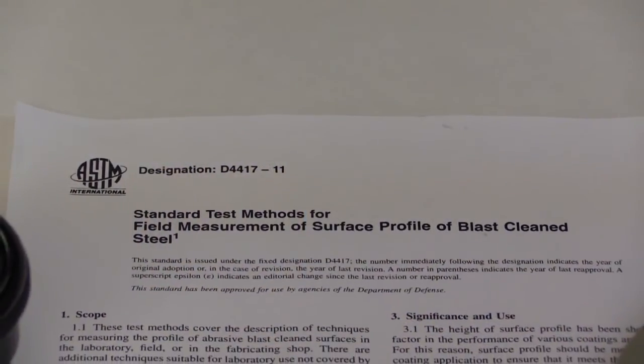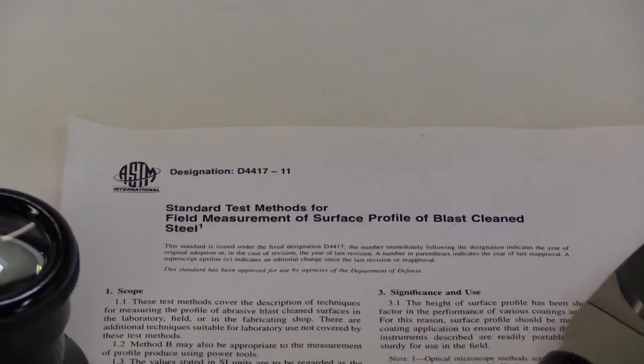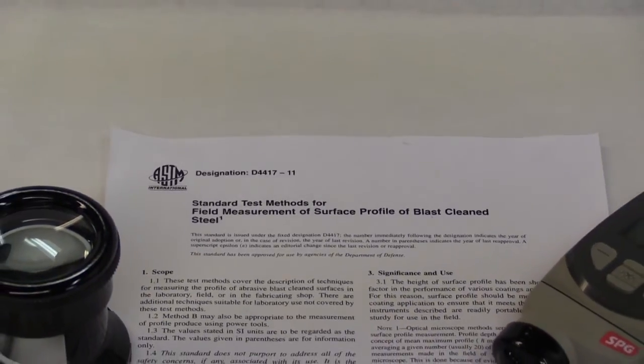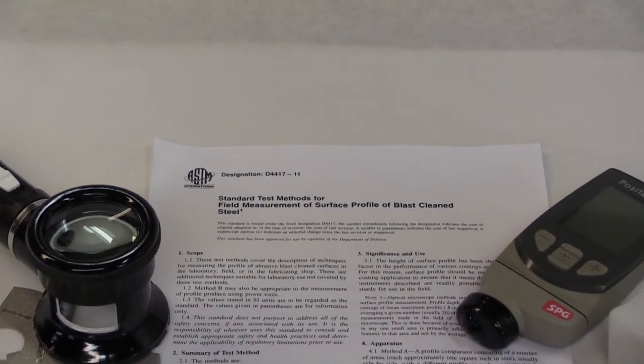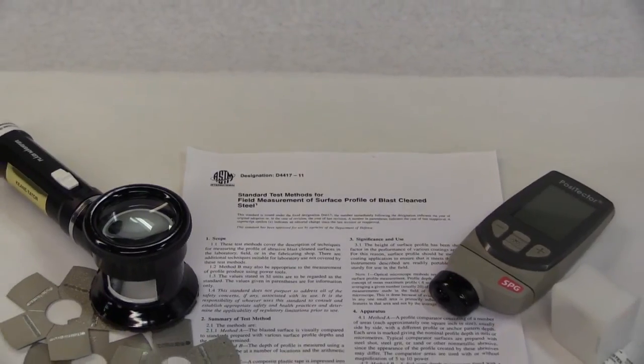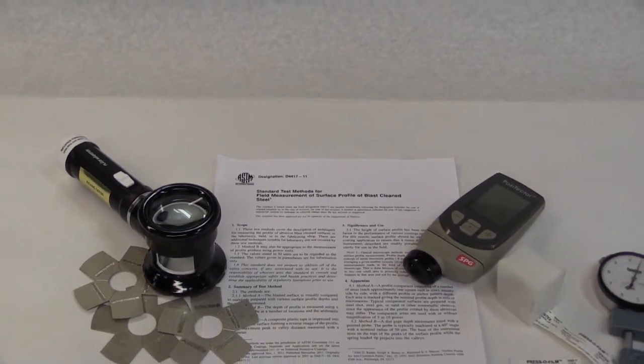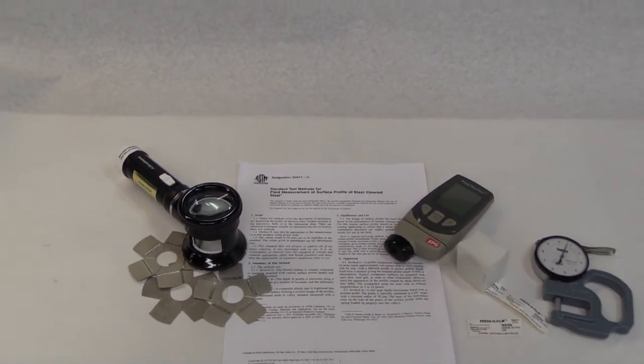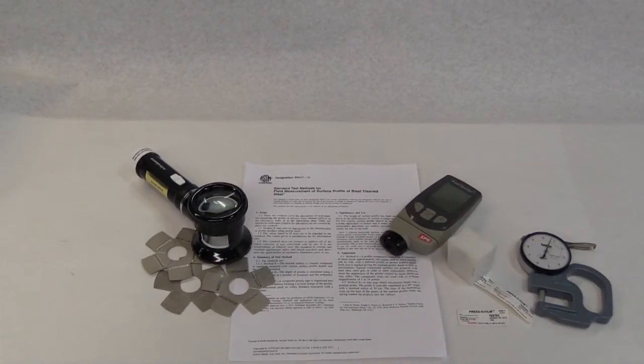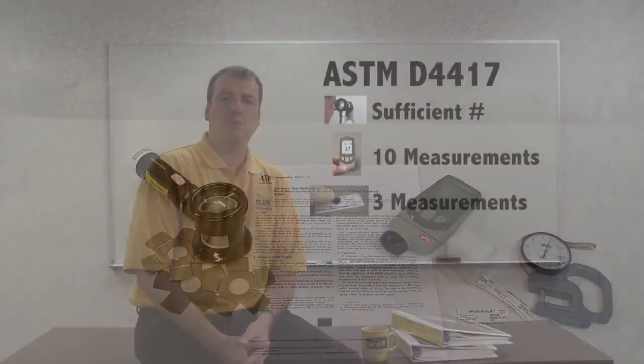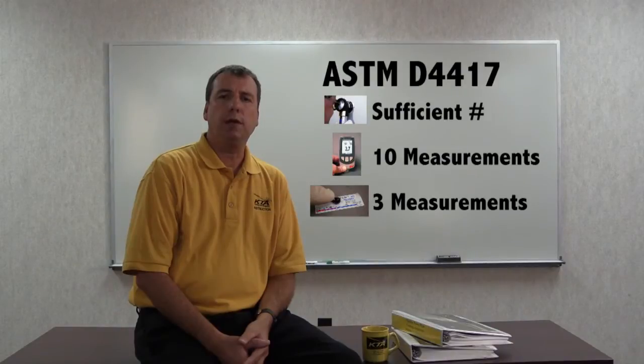ASTM D4417 describes three of these methods and includes Method A, Visual Surface Profile Comparator, Method B, the Surface Profile Depth Gauge, and Method C, Replica Tape. The number of readings to determine the average surface profile at each location is based on the number required by ASTM D4417. The average of the readings at each location is the location average.